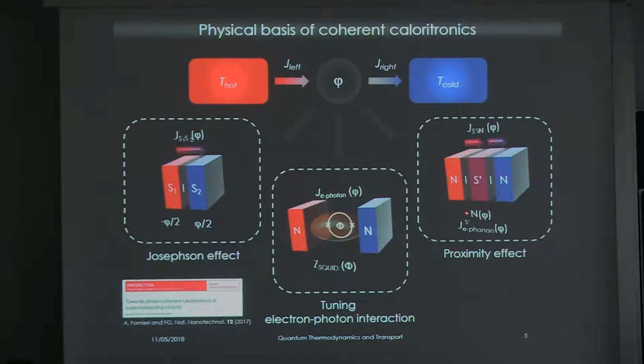For instance, the density of states becomes phase dependent, the specific heat and the entropy of this engineered superconductor become phase dependent. The electron-phonon coupling, so the exchange of heat between the electrons and the phonons in the structure, becomes phase dependent. Okay, so in some sense, a proximity superconductor is a very ideal candidate because it can be engineered, thanks to the phase, to have a specific response to heat.